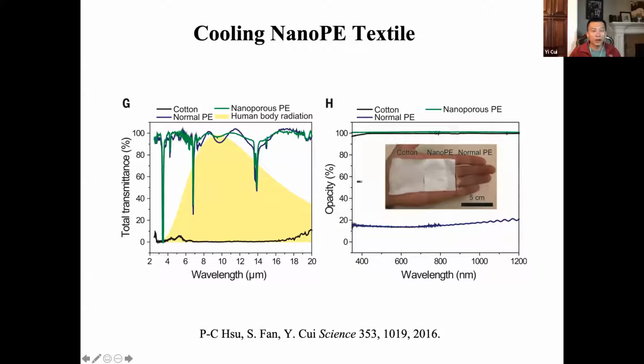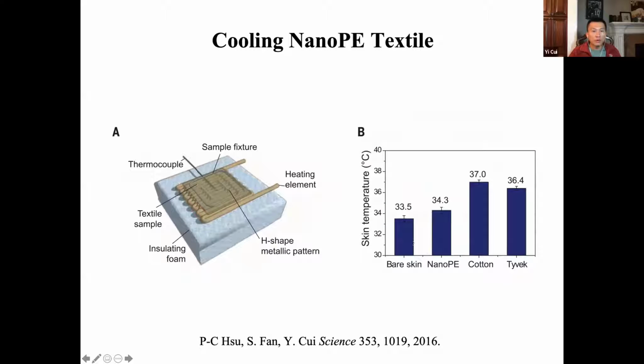And we have about 90% infrared transmittance. We can get to that level, but visibly it's white color, already opaque. We measured this sample and compared with the bare skin, in a fixed ambient temperature, with a fixed power mimicking the skin using this hot plate. Well, bare skin without wearing anything, 33.5 degrees Celsius, and nano PE 34.3, a little bit higher, but a lot better than cotton, about 2.7 degrees Celsius cooler than cotton. So we were quite excited about this. It's a very clear cooling effect right there.